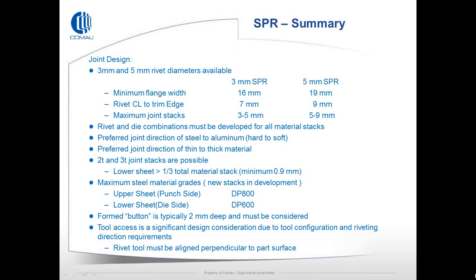A brief summary in terms of the SPR, self-pierce riveting. There are normally 2 rivet diameters, 3 and 5, but there are some other bespoke rivet diameters. Some current summary in terms of minimum widths: 16 and 19 mm. Center line to trim edge is quite reduced down to 7 and 9 mm. Maximum stack joints: 3 to 5 for the 3 mm and 5 to 9 for the 5 mm. But again, emphasizing that the stack and configuration is critical to the process.